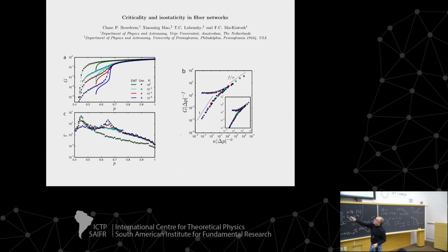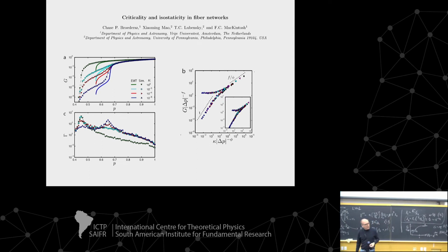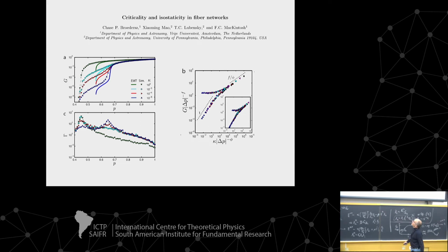That's the isostatic point. Now, it's plotted in a slightly funny way because we're taking a particular lattice, a triangular lattice, and diluting it, so p is the bond probability. So this happens to be 4, okay? Well, around here somewhere is 4. 2/3, basically, would correspond to Z equal 4 for a triangular lattice.